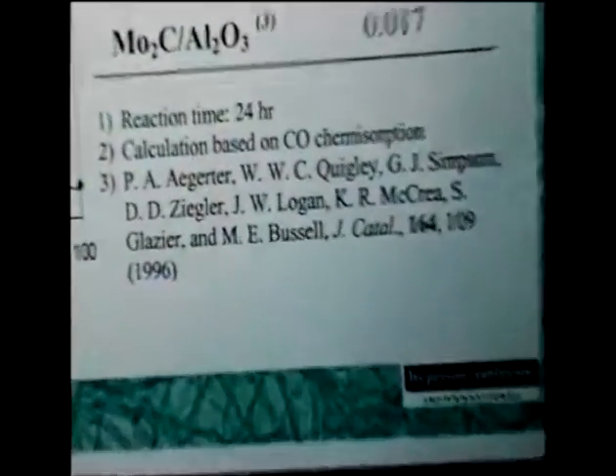This is a pretty industrial project. They are interested in producing things, so per gram or per unit of volume is what they are interested in, and it's very reasonable, this type of curve, because two things are going in different directions: surface area decreasing, but number of sites increasing as the molybdenum carbide changes. The one that we like best is if we normalize those things.